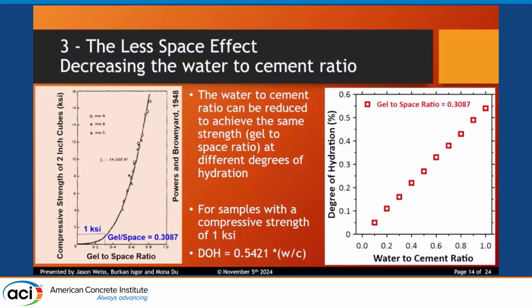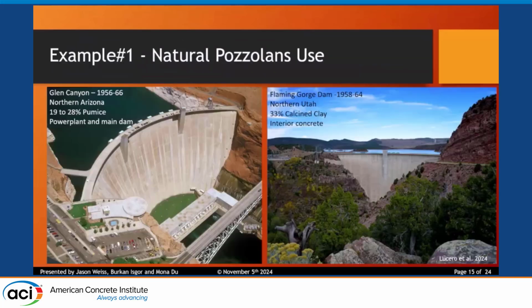You can actually figure out how much hydration had to happen in different water to cement ratio systems to get to that same gel to space ratio. And what you notice is, as you go to a lower water to cement ratio, it requires less degree of hydration. I've used this because it has been the foundation of what we've understood about cements for the last 80 years, but we can do the exact same thing with thermodynamic modeling by adding in other components, the calcined clays, the slags, the fly ashes, and calculating that gel space ratio. And we do this all the time.